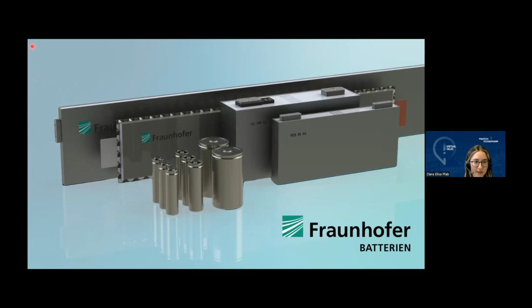Perfect. So one last question, I think. So what energy densities are realistically expected for solid state batteries? Maybe 400, 500 watt-hours per kilogram compared to 350 for lithium-ion batteries. 300 is already real. With increasing amounts of silicon, this can be 350, maybe a little bit more. And the lithium-based solid-state battery, in fact, doesn't need an anode because the lithium is already in the cathode. So maybe 500 could be possible.